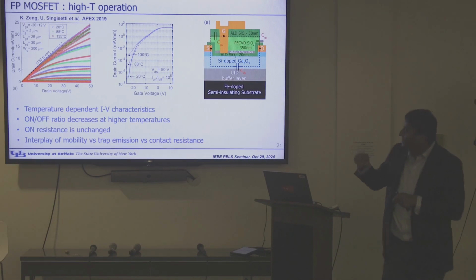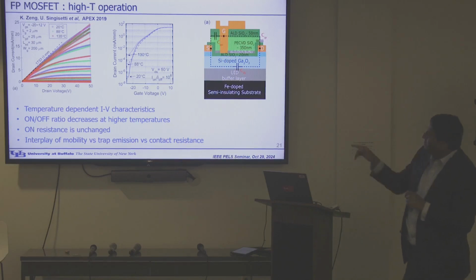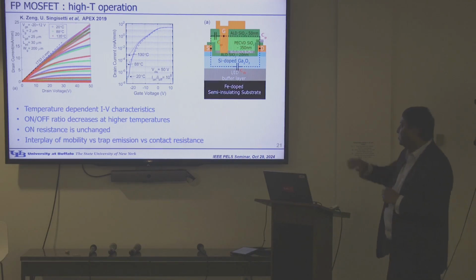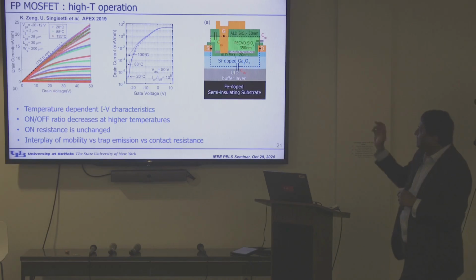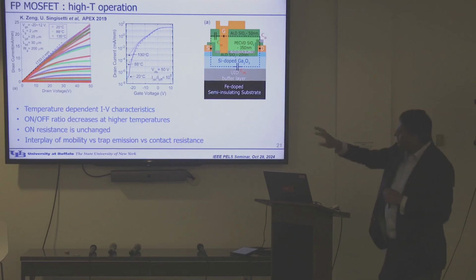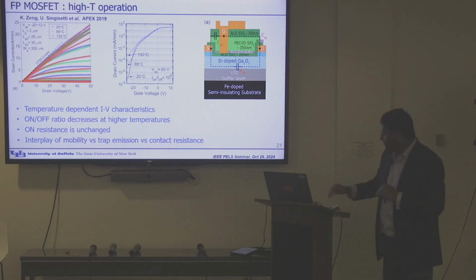So the figure on the left is showing the temperature dependence IV. Interesting thing to note is you can see the on resistance is not changing with the temperature at all. It's almost constant, almost zero coefficient, right? You can see it's an ultra widebandgap semiconductor, so even at 130 degrees Celsius, we've got good on-off ratio. So the on resistance not changing is a little bit of an interesting interplay. As you go to high temperature, the mobility drops, the contact resistance improves in the widebandgap semiconductor, so a kind of balance is there. You get a constant resistance with temperature.